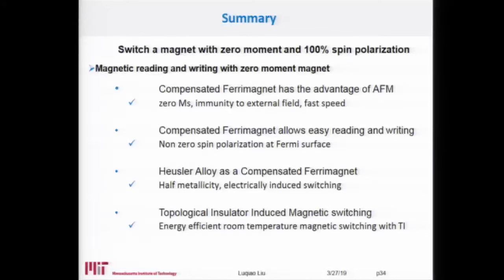Okay, so basically today, my topic is mostly about how to realize magnetic reading and writing with some zero moment magnet. Particularly, I talked about the concept of compensated ferrimagnet. Similar to antiferromagnet, compensated ferrimagnet has zero moment, so you can make very high density and high speed spintronic devices out of them. But at the same time, it allows easier reading and writing operations compared with antiferromagnet, because on the Fermi surface you have non-zero spin polarization. Finally, we also look into Heusler alloy as another potential candidate for compensated ferrimagnet. And we also show that using topological insulator, we can potentially combine low switching energy together with the fast switching dynamics that is obtained on those zero moment magnets.